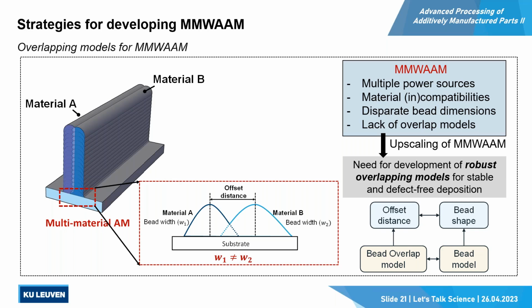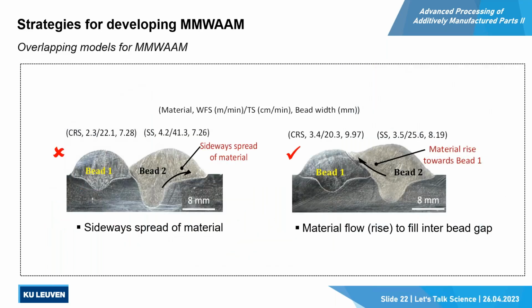In the next slide, if I want to show the significance of this distance, you can compare these two beads, which have been deposited with a slight change in the offset distance. On the left, you see when the second bead is deposited next to the first bead, the molten pool has spread to the other side, and there is a large gap between bead 1 and bead 2, and this gap will remain in the further layers and will result in a lack of fusion.